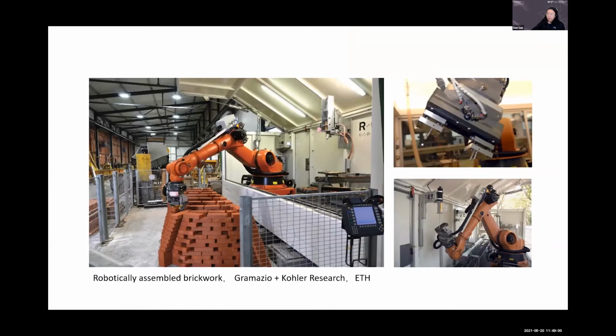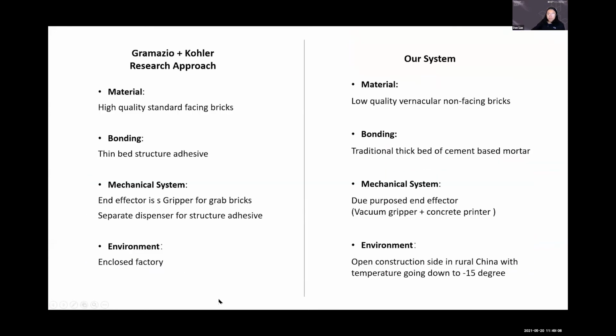When we talk about bricklaying, there is quite a lot of work on assemblies and brickwork. Based on that, we started to look at what would be the bridge from the lab environment. This project is actually in rural China, so it is not in our ideal lab environment, and the budget does not allow us to afford customized, highly accurate bricks and structural mortars. So we're dealing with low quality vernacular non-facing brick, and for the bonding, we're staying with a normal traditional thick bed of cement mortar. We were thinking of creating a dual-purpose end effector, a mechanical system that could both accurately place the brick as well as print the mortar at the specific place of the overlapping.